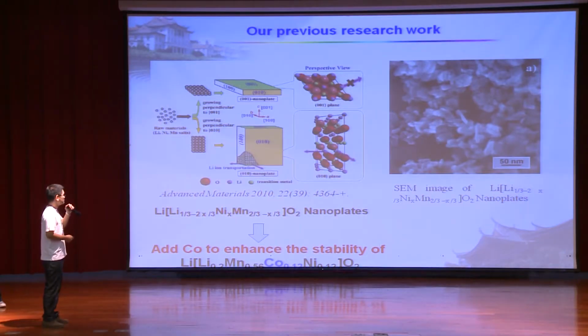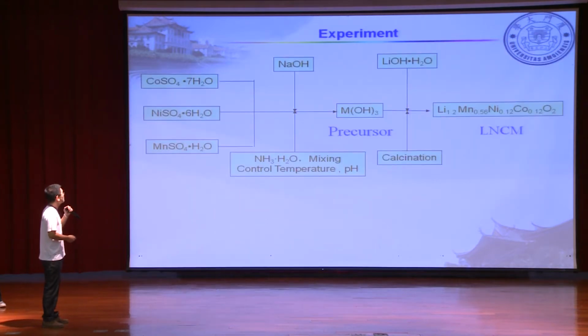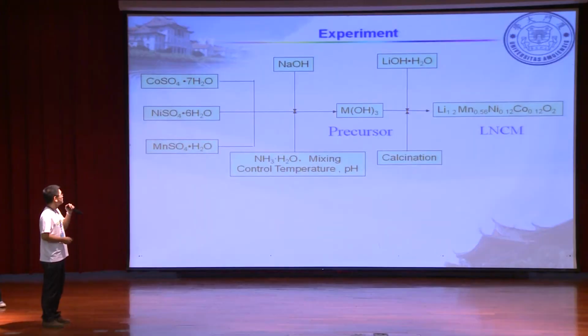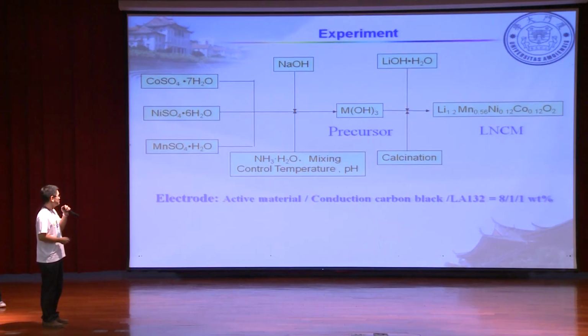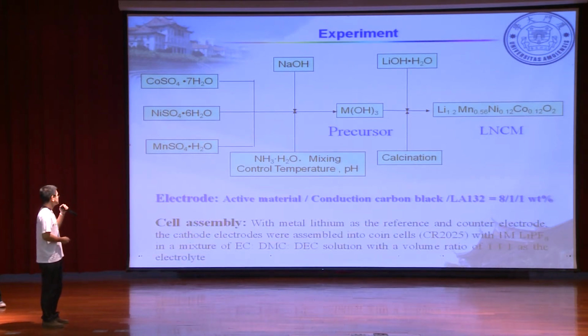Currently, we designed a new kind of lithium-rich cathode material by adding cobalt to enhance the structural stability. This is our preparation procedure. Firstly, we mix the sulfates of cobalt, nickel, manganese with ammonia and sodium hydroxide. And then after high temperature calcination of the precursor, we could get our product, LNCM. And the electrode was prepared by mixing active material, conductive carbon black, and binder. And then we assemble the electrode into coin cells in a glove box and test their electrochemical performance on an instrument.